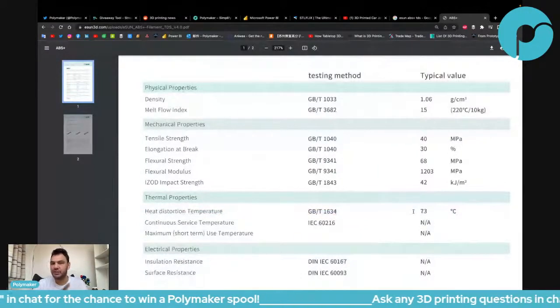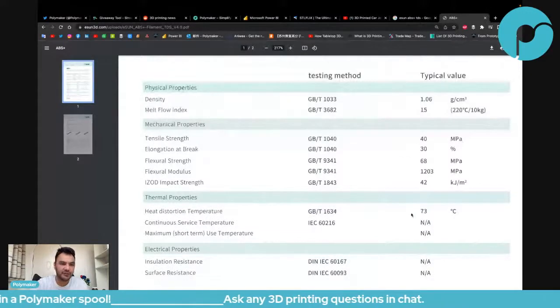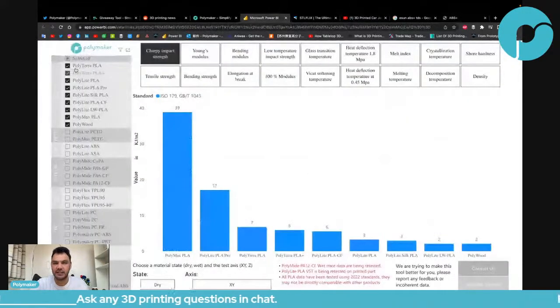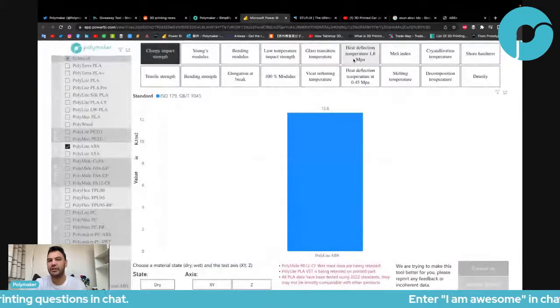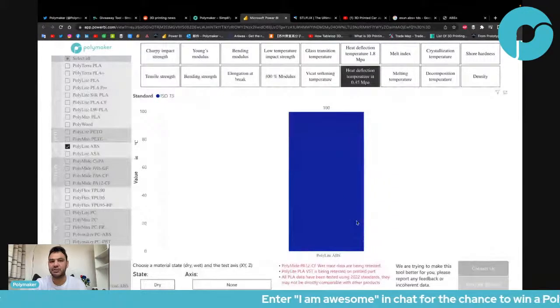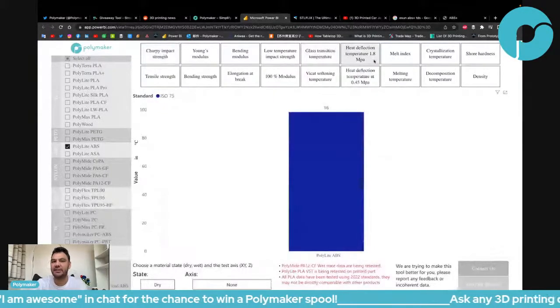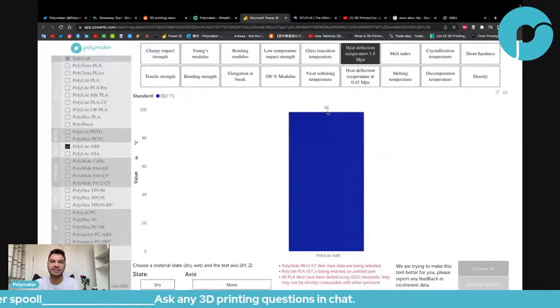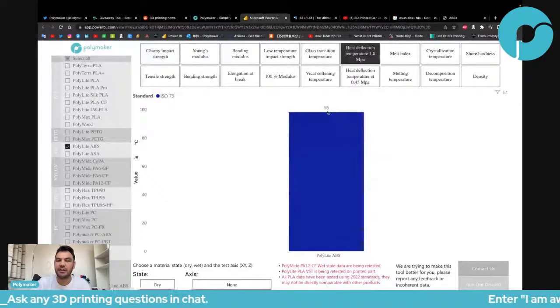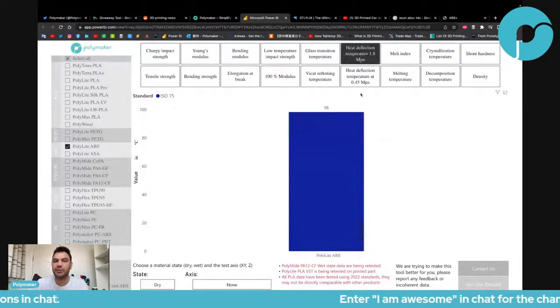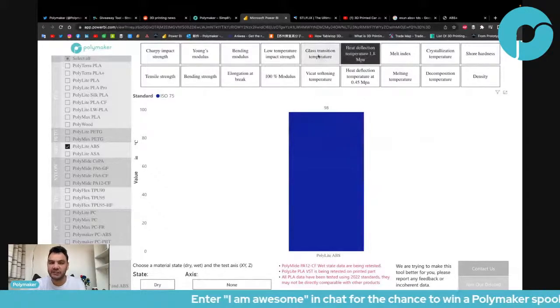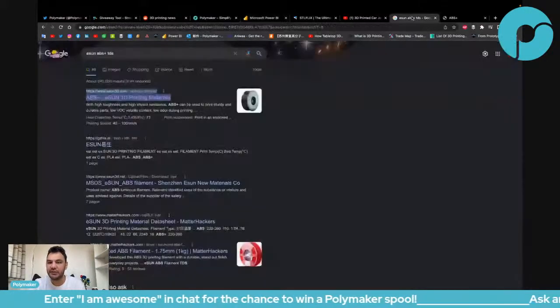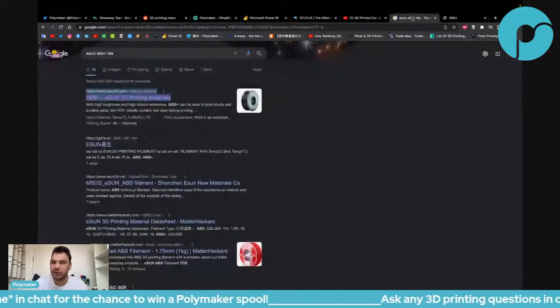So the HDT for amorphous material should be pretty much the Tg. If you go and check our PolyLite ABS, and then check the HDT, you see it's exactly 100 degrees. And the glass transition temperature is 101 degrees. So even if you take the HDT at 1.8 megapascal, it's 98. Why? Because it's pretty sharp between the rubbery state and the glassy state. So the HDT, whatever the stress, to a certain extent will more or less be the glass transition temperature. So when I saw that the ABS Plus was 73 degrees C, it means their Tg is very low, to around 73 degrees.